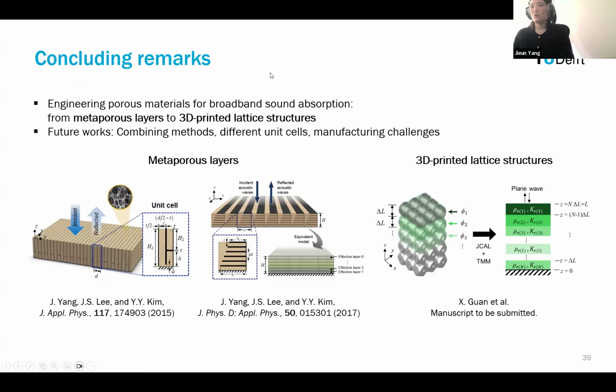So to conclude, I showed these 3 works about engineering porous materials to get a broadband sound absorption. For the Metaporous layer, I show the approach in including some rigid partitions to modulate the wave propagation length and also sound wave velocity inside the homogeneous porous layer. And for this 3D printed lattice structure, I show the approach to find optimal grading profile along the thickness of the sound absorber.